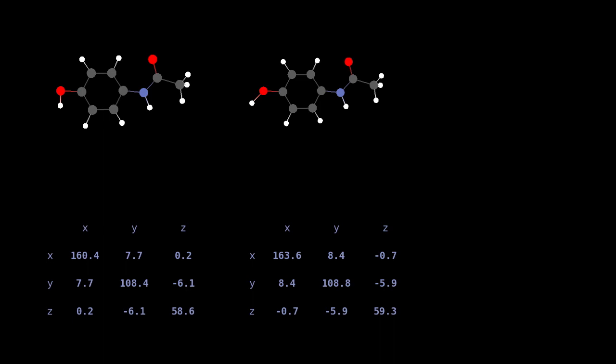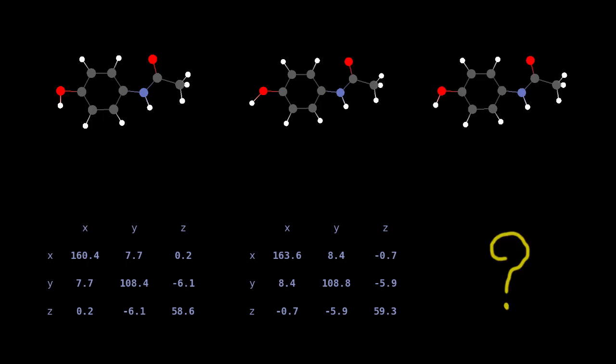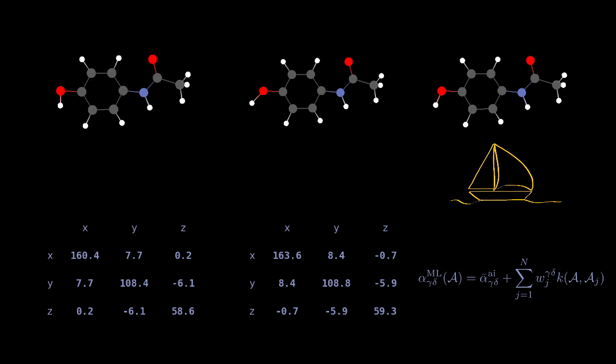Suppose we know, say, the polarizabilities of two different structures, and would like to interpolate the polarizability of a third configuration without resorting to any ab initio calculation. To achieve this, we use in this work Gaussian process regression approaches, a type of supervised machine learning, offering us a way to navigate through all the configuration space and learn the mapping between a geometrical configuration and its corresponding polarizability tensor.